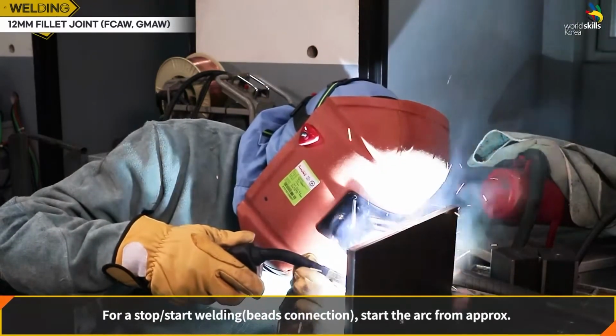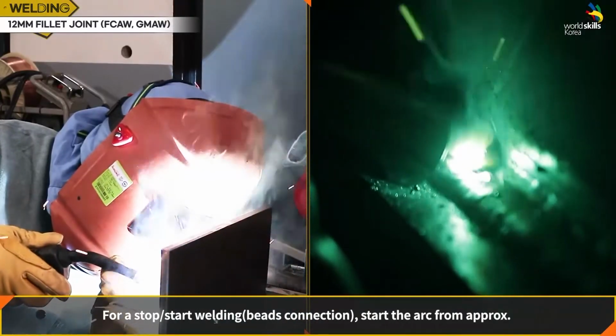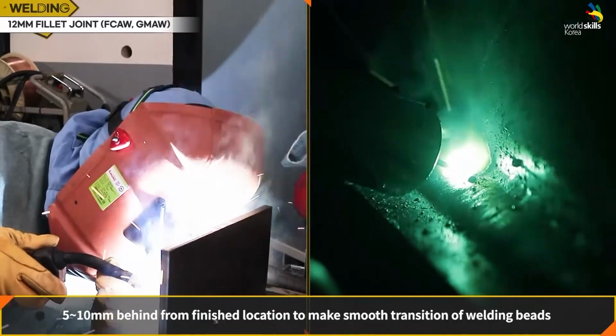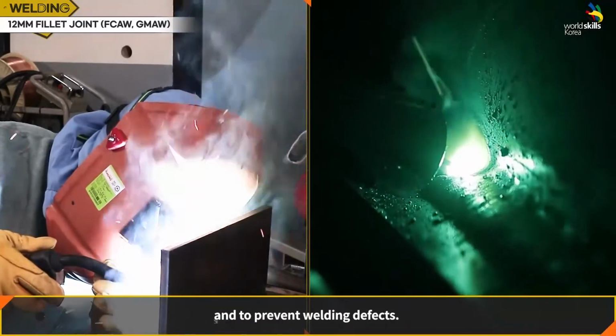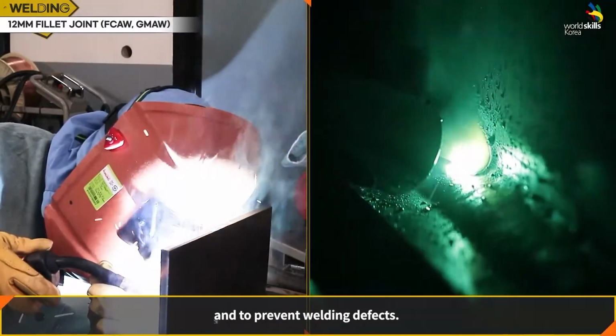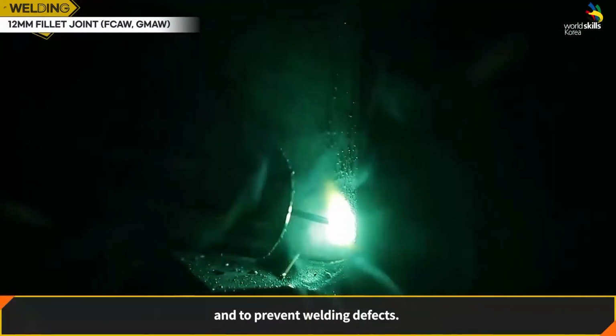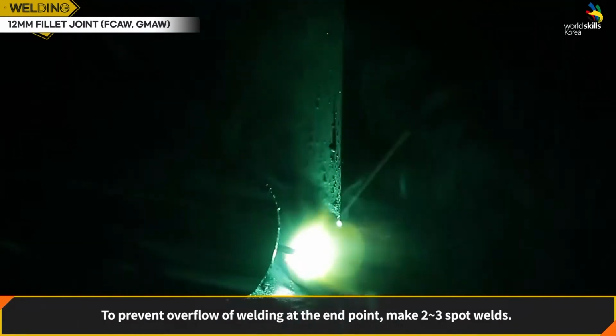For a stop-start welding bead connection, start the arc from approximately 5 to 10 millimeters behind the finished location to make a smooth transition of welding beads and to prevent welding defects. To prevent overflow of welding at the end point, make 2 or 3 spot welds.